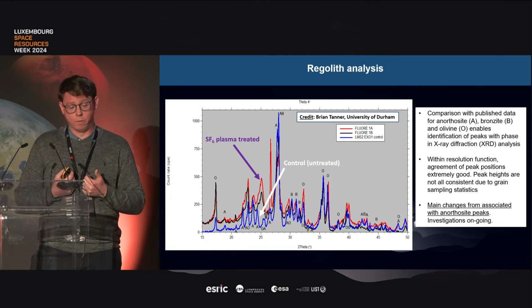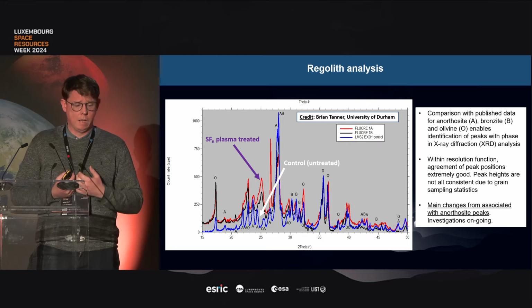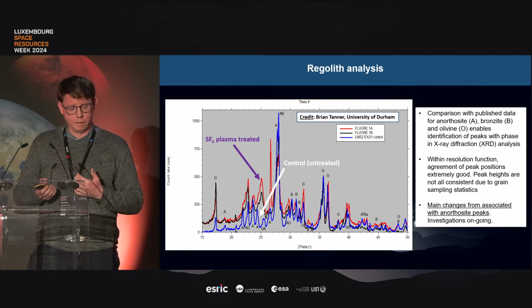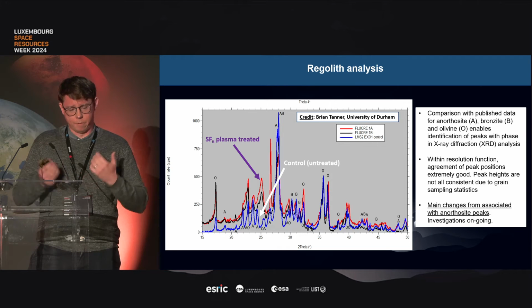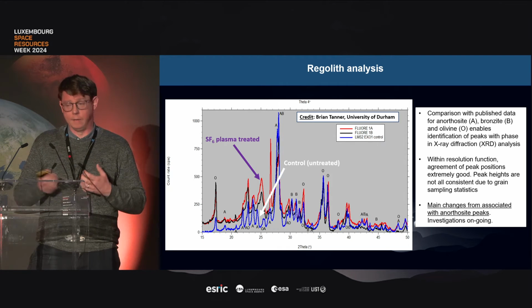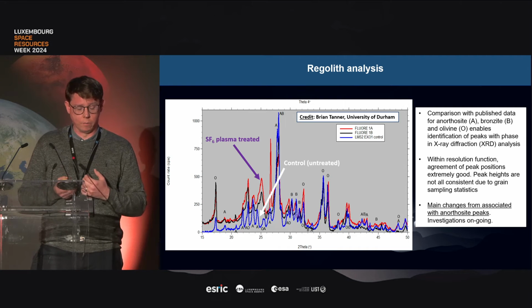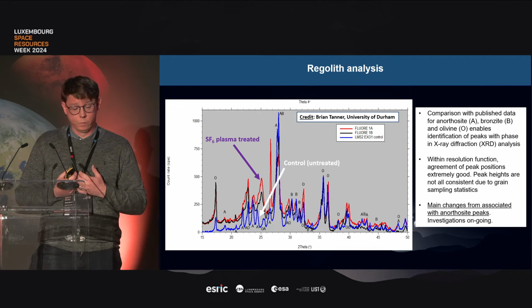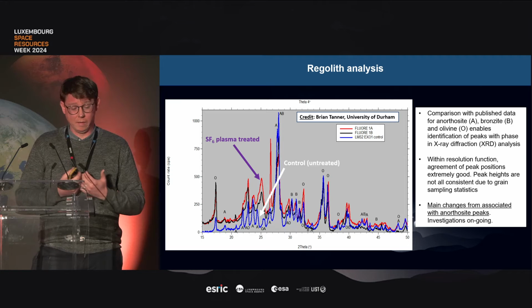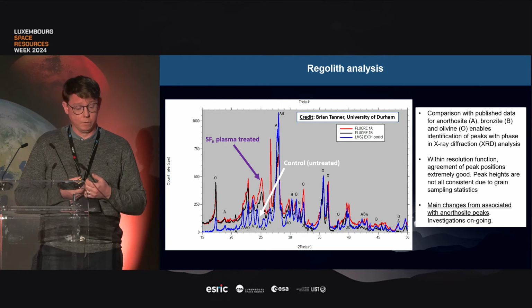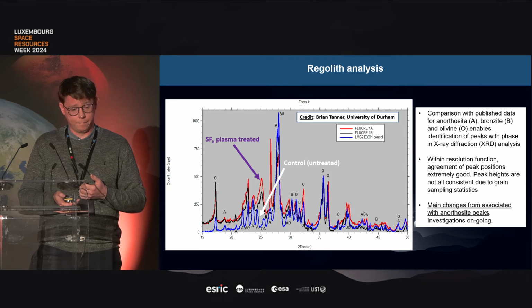So we're also looking to analyze the crystal structure with our collaborator at the University of Durham, Brian Tanner. Brian has taken the XRD profile for the main mineral components of interest, anorthosite, bronzite, and olivine. And he's used this to baseline the XRD profile for the LMS1 regolith. And then he's been looking at the changes only recently to do with the plasma. So he's seeing that the changes are mainly associated with the anorthosite peaks, but we don't have much more insight other than that at the moment. So investigations are ongoing into that.